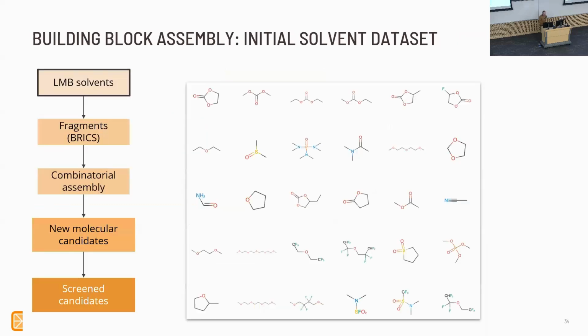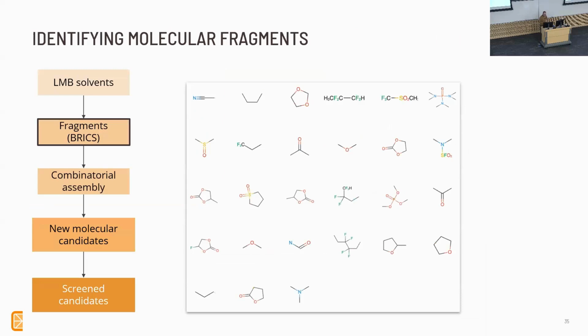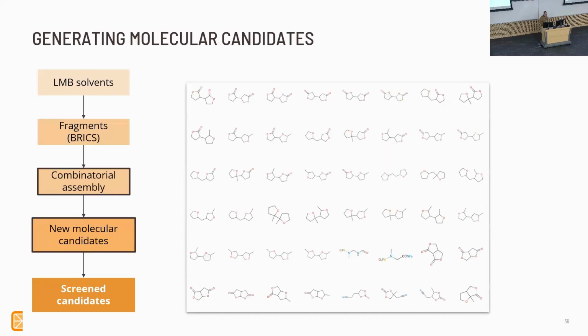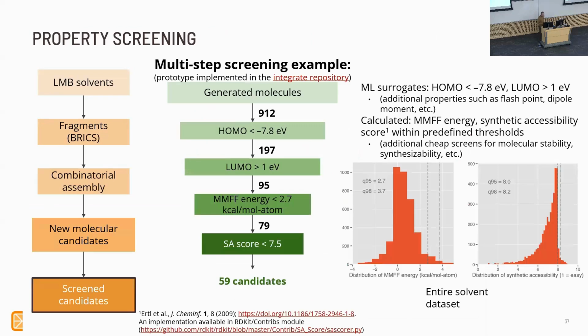So just walking through this process, here's the pool of good molecules that we started with from that first plot. We broke it down into a bunch of fragments. So these are the constituent fragments that created these good solvents. And then we just combinatorially developed new ones, and this is just a sample of them. And then we screened them by going through, of let's say a couple hundred, 900 or so molecules, those that have a HOMO less than negative 7.8, a LUMO greater than 1.